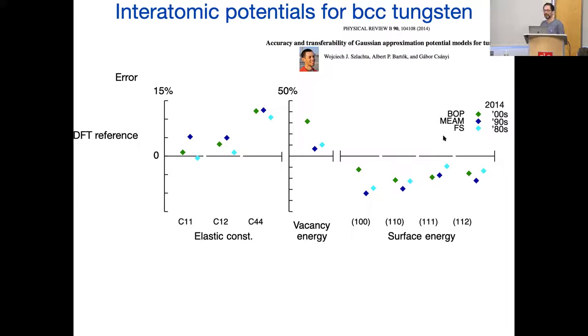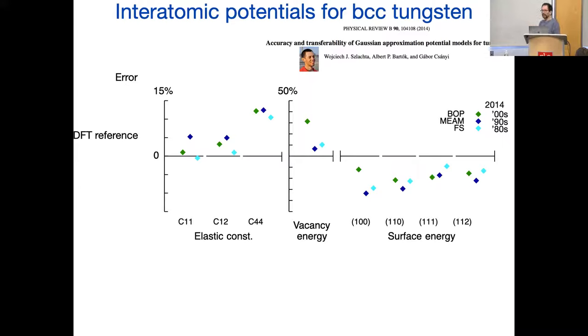I want to show you the kind of revolution you get when you achieve this. Here's tungsten — two to three decades of modeling tungsten empirically, the state of affairs before 2010. Here are properties: some elastic constants, vacancy energy, surface energy, percent errors with respect to DFT. You see that 30 years of development hasn't made much difference. Then you come along with machine learning methods — data-driven, many-parameter fits — and you get dramatically better results.